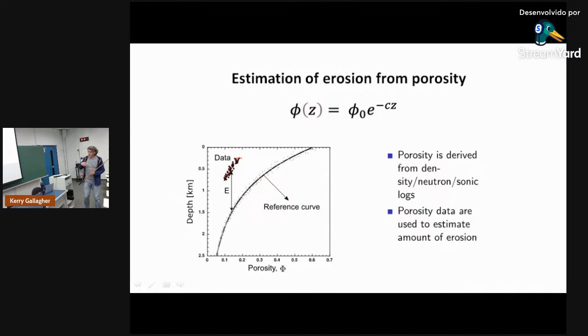And one way, something we can do with porosity data, I didn't talk about this with you before, I think, but porosity reflects compaction. The sediment at the surface is quite porous, but as it gets buried, it gets compacted and the porosity reduces. But if that layer of rock between my hands goes up to the surface because of erosion, it stays compacted, it doesn't expand. Okay? So the porosity at the surface would be low compared to what we'd expect if the rock had not been subjected to a lot of erosion, a lot of missing section.